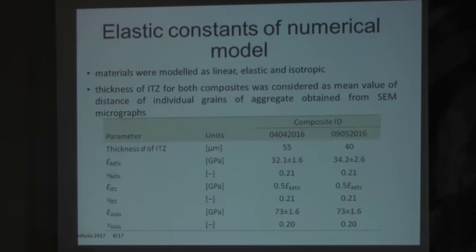So the materials were considered as linear, elastic, and isotropic. They were defined by their elastic constants, Young's modulus and Poisson ratio. As I told you, the thickness of the ITZ was taken into account from the microscopic measurements. The modulus of elasticity of the matrix was taken from the fracture experiments which we performed, and the modulus of elasticity of the ITZ was determined using the so-called generalized self-consistent scheme. It was taken as half of the modulus of elasticity of the matrix.